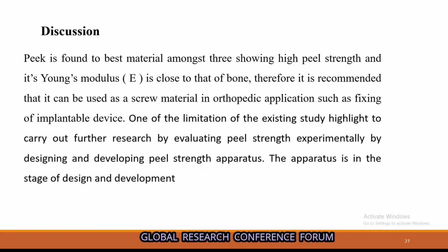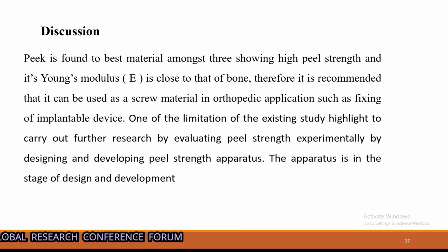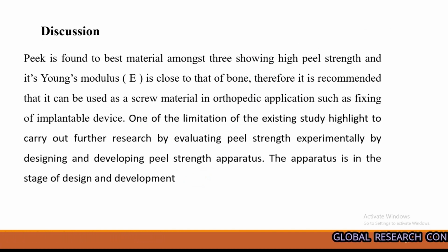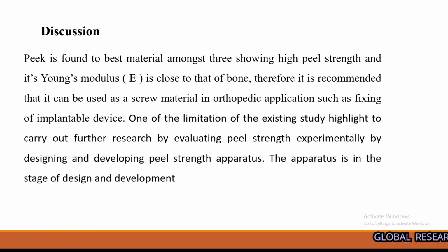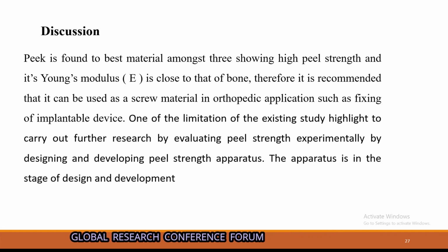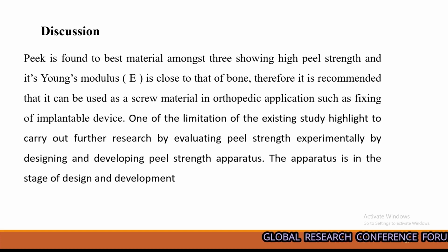This is the discussion. PEEK is found to be the best material among the 3, showing high peel strength and Young's modulus close to that of bone. Therefore, it is recommended to be used as a screw material in orthopedic applications, such as fixing of implant devices. One of the limitations of the existing study is that it highlights the need for further research by evaluating the peel strength experimentally. That is very important, by designing and developing a peel strength apparatus. So the apparatus is in the stage of design.